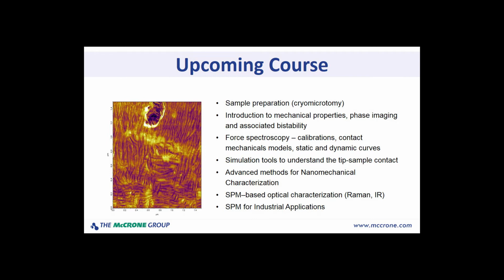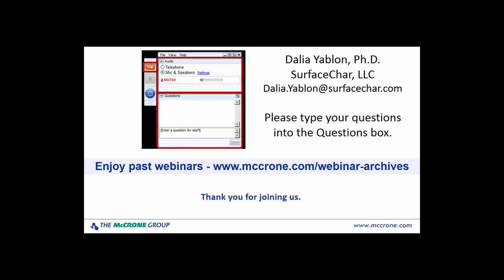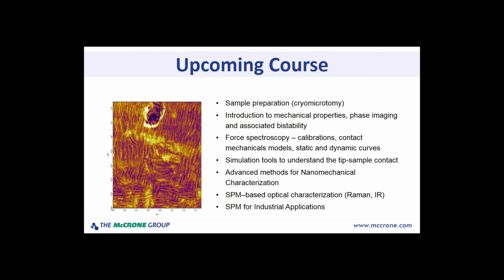Okay, one final one that comes in, and maybe this will be the final question. Is there any literature on how to pick the correct cantilever, i.e. for different samples? So that is one of the $64,000 questions when you do AFM. So you really have to, I would say, understand the tip sample physics and interactions in order to be able to properly select your cantilever for the measurement. There are certainly some guidelines, some formulas that we all base it on, but if you really understand what the nature of the interaction between your tip and sample is, that's the best way to pick the cantilever. The cantilever matters a lot. The spring constant, its material, the shape of the tip, and it's really important. It's probably the most important parameter you pick when you run your AFM.